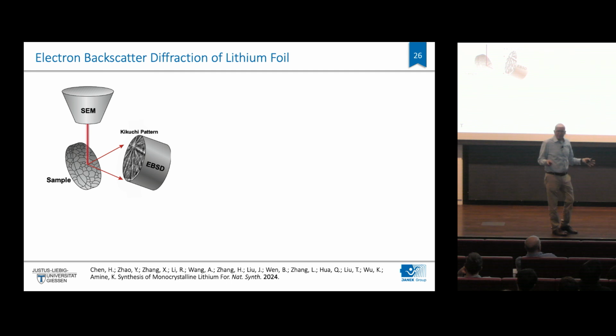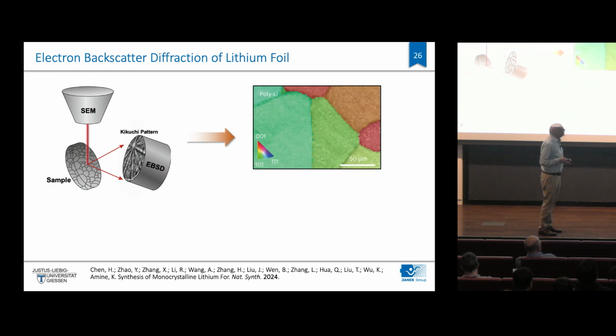The secondary electrons can be used to get all these nice pictures, of course, of the surface with the electron microscope, the morphology, but you also get information from scattering, diffraction information, essentially. And that can be used from a near-surface region to get information about the phase identity and the orientation of the grains. That is extremely difficult with the alkaline metals, because the surface always reacts with everything, and you have to be extremely careful, and they managed to have a workflow that is careful enough.